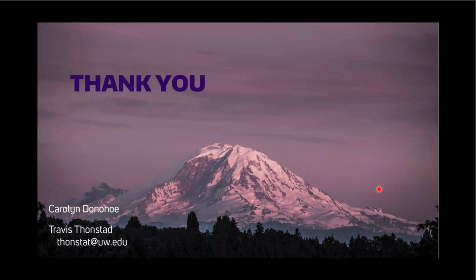Okay, no, that's fine. Another question that came in during the webinar said you had a 25% change with temperature, and they want to know if that was up or down the curve. They felt it made a difference. Absolutely. What we found with the testing was that the relationship in this range of temperatures was roughly linear. If you increase the temperature 40 degrees from room temperature, you see about a 25% decrease in strength. Conversely, if you cool the material down 40 degrees Fahrenheit from room temperature, you get a 25% increase in strength or stiffness. That just has to do with the behavior of polymers. And like I said, in this particular range, because we're to the left side of the glass transition temperature, we're seeing a roughly linear slope.